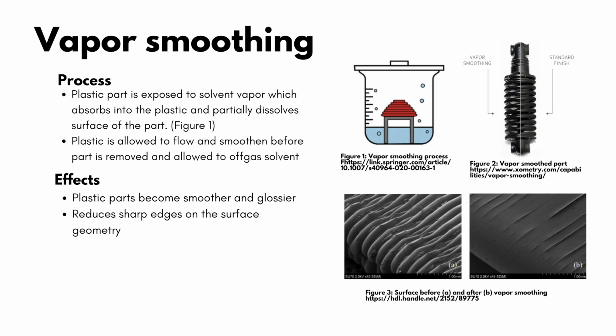Now this can cause defects such as drooping, but it does have some good effects when you zoom in. The figure on the bottom shows the layer lines of a MEX part being smoothed out with vapor smoothing. Now this can increase part strength by reducing small cracks that could cause weak spots when a load is applied.